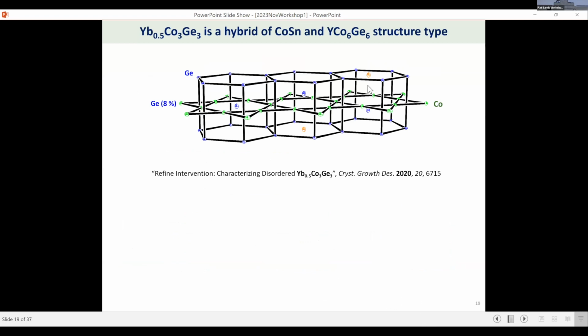When we do the refinement, we have one of these 3 configurations, but it is an average of all of the 3 configurations. And so we're excited to see that this is not 166, it's not cobalt tin, but that rare earth can be encapsulated.